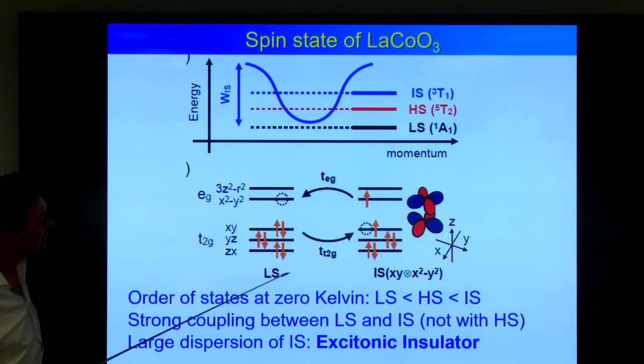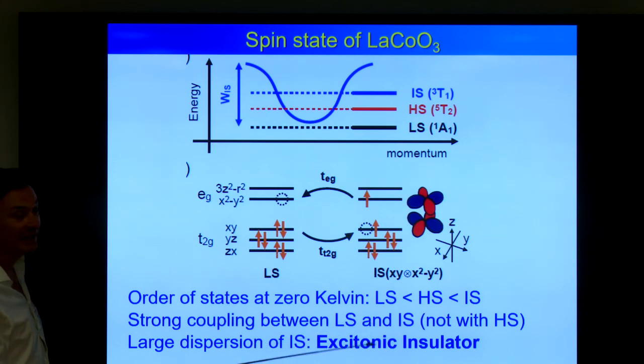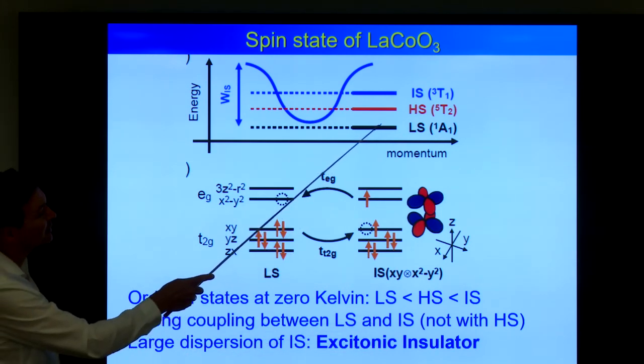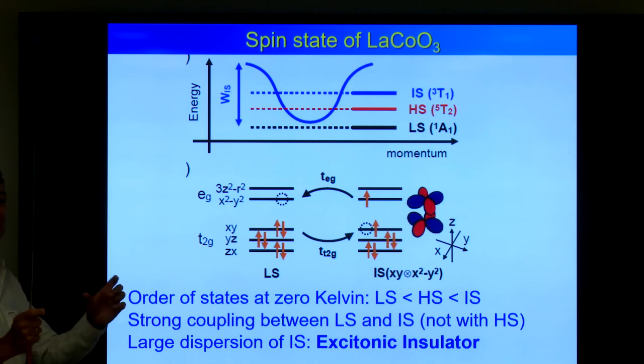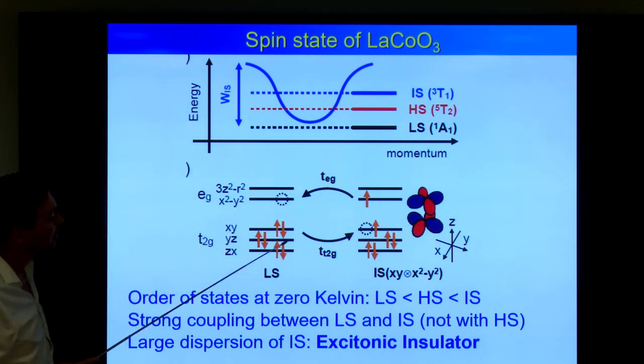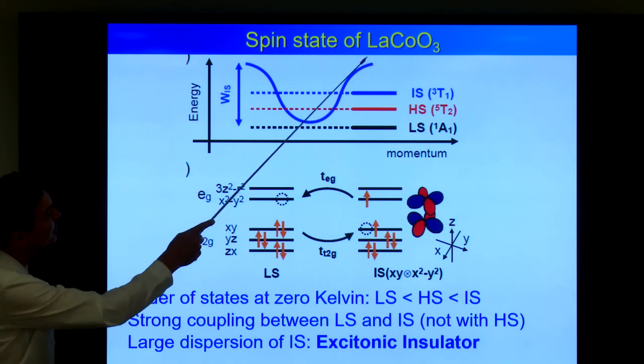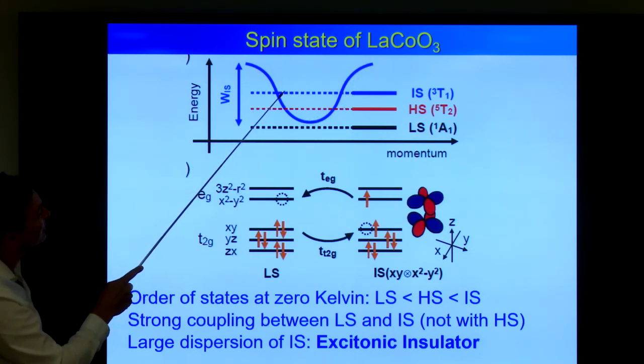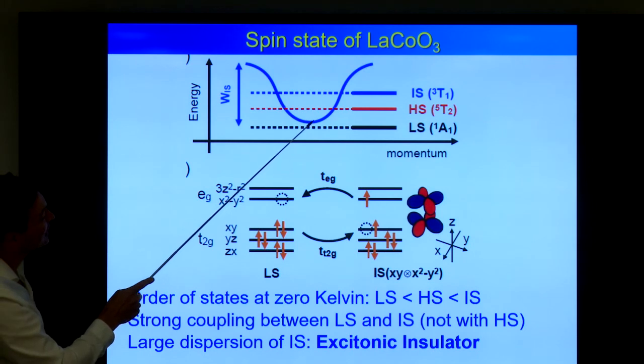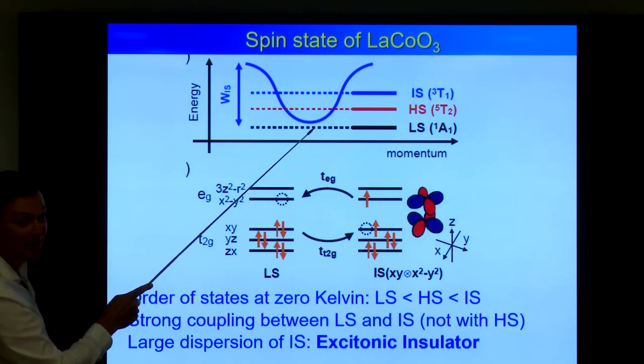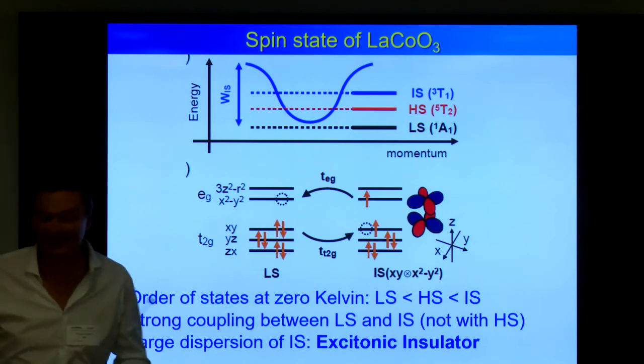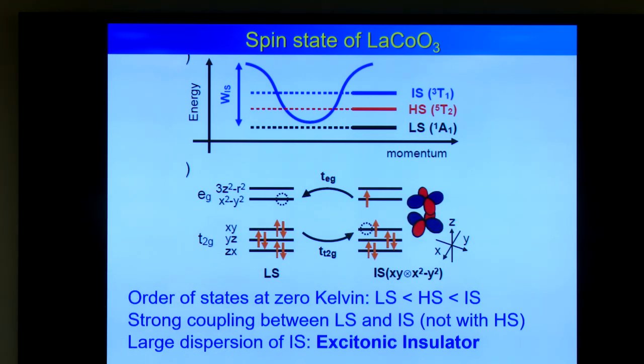And the intermediate spin can hop very strongly and can couple to the low spin. So you have very strong t2g and eg hopping between sites which are low spin and intermediate spin. So if you want to study the dynamics of the electron transfer in the system, you can never switch from low spin to high spin. So they are separate islands in the system, but you can hop from low spin to intermediate spin. If the dispersion of this intermediate state becomes very large, in some parts of reciprocal space it can fall below the low spin, and then you have an excitonic insulator. It's nice. It's a hot topic if you're in this field.